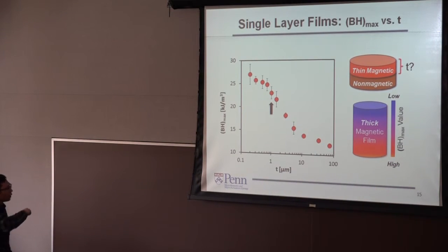So one other thing you can find out from this plot is that you can determine the magnetic layer thickness in this laminated structure, right? Certainly, given the assumption that you can retain or preserve the thin film properties, the thinner the magnetic material you choose, the better the property. But there is a trade-off, right? If you have to choose a very thin layer, the process complexity will increase. But definitely you won't want to choose something that has already sharply decreased. Right? So 1 micron, that's what we choose over here to be the magnetic layer thickness.